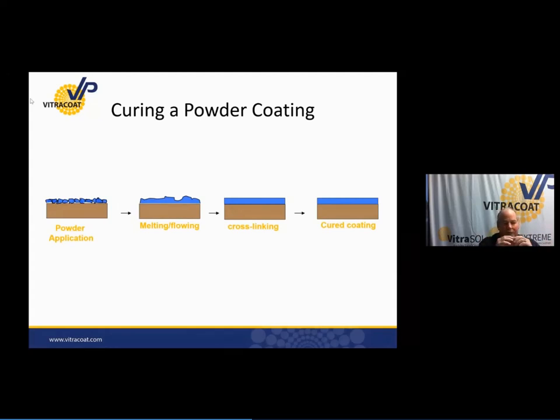I also wanted to talk a little bit about what gel meant, just so you're familiar with what I mean by that term. On the far right hand or left hand side of the picture, it showed the powder and the particles laying on the substrate. And then as you subject that powder to heat, radiant heat or convection heat, it starts to melt and it starts to flow. And over time, eventually, it will completely cross-link, forming a film. The gel is in that melt and flowing section.